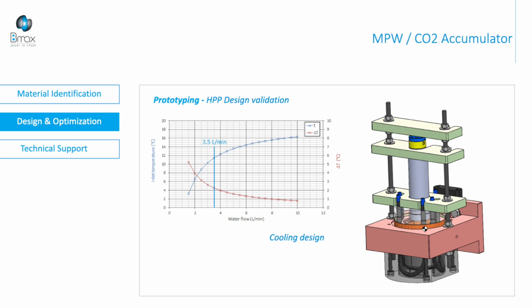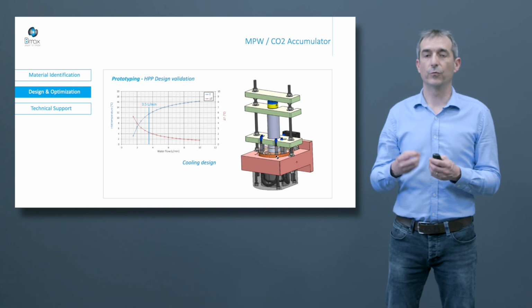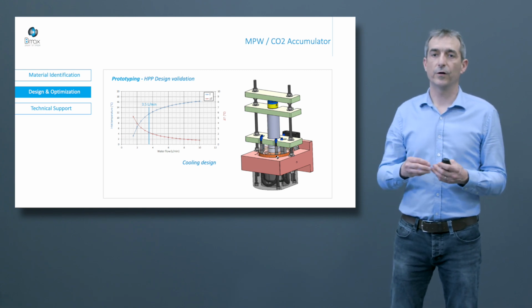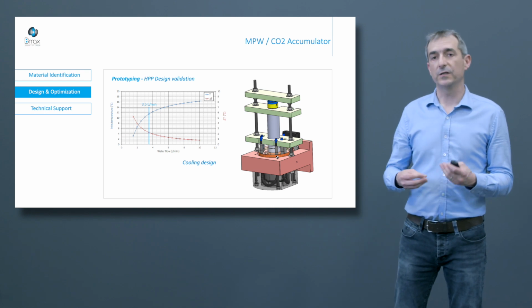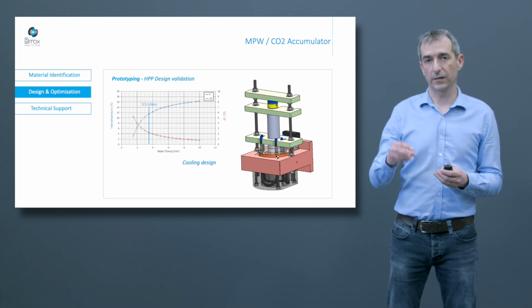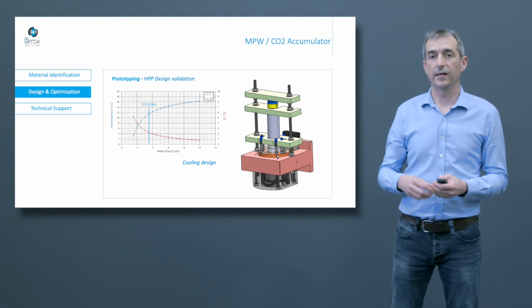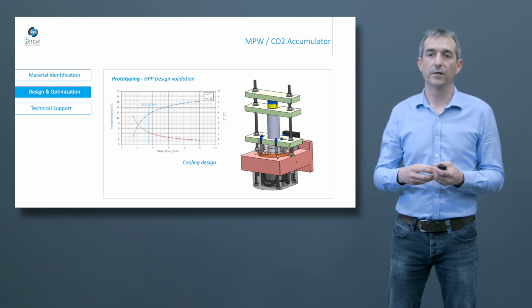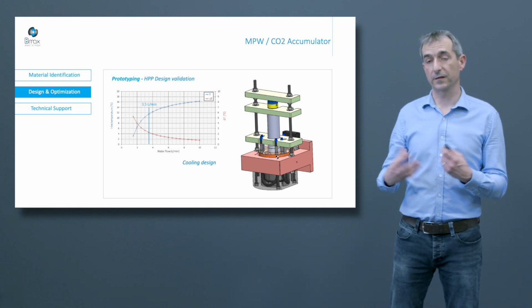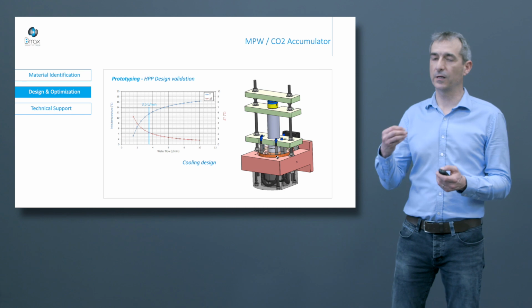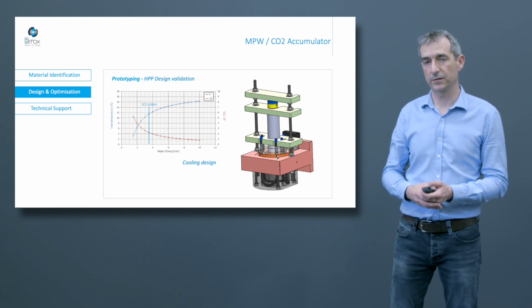Thanks to simulation, we can calculate the temperature increase during one shot. And we can calculate the temperature during the production phase, according to the production rate. So thanks to the simulation, we can say with a water unit able to deliver 3.5 liters per minute, we need a water inlet temperature of 12 degrees, and the temperature increase by the cooling system is a few degrees. So thanks to the simulation, we validate the HPP configuration and we design the cooling system.